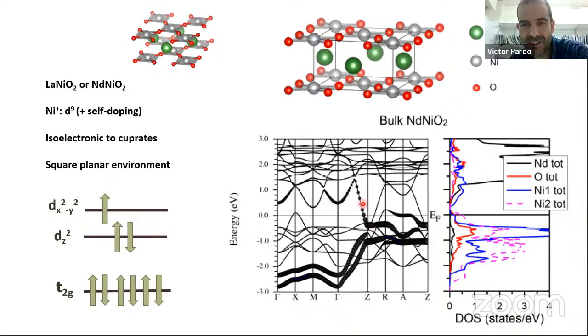No, you have this band that has some dz² parentage mixed with the neodymium f bands. So there's a strong mixing between the nickel and the neodymium or lanthanum bands that produces these hugely dispersive bands. So this produces what is called a self-doping effect. This means that the dz² band is partly unoccupied, and the rest of the electrons come from the neodymium or lanthanum. So the nominal filling is d9, but there's a different number of d electrons coming from the nickel because of this self-doping effect.